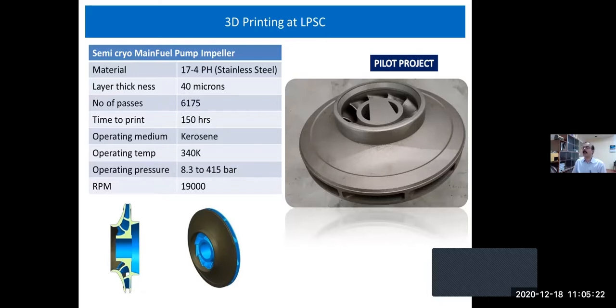So we have 3D printed the main fuel pump impeller. The part that you are seeing on the right is the 3D printed part. The material is 17-4 PH, a precipitation hardened high strength stainless steel. You have a layer thickness of 40 microns, which means this is built up of around 6,175 layers. The time to print is around 150 hours. The operating medium is kerosene and it operates at a temperature of around 340 K. The pressure is very important, 8.3 to 415 bar, very high pressure, and it runs at around 19,000 RPM.